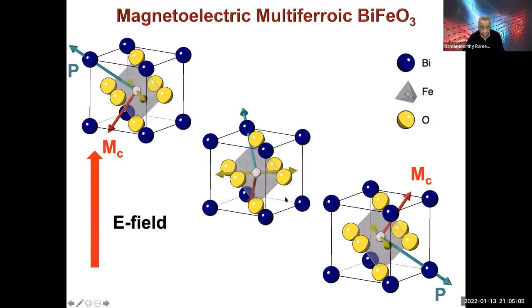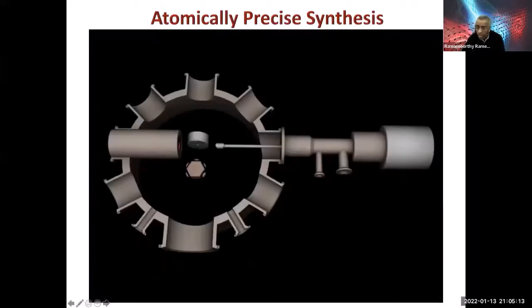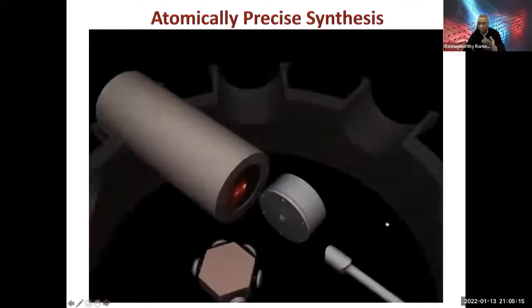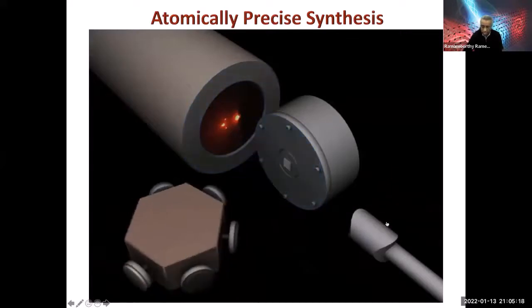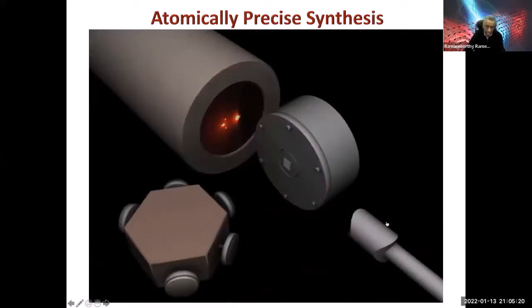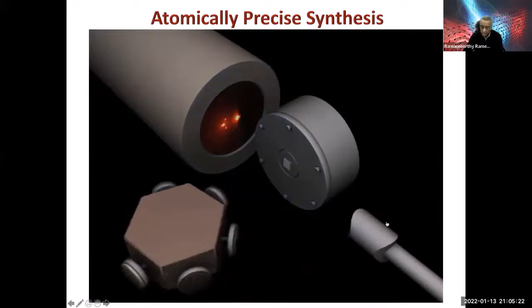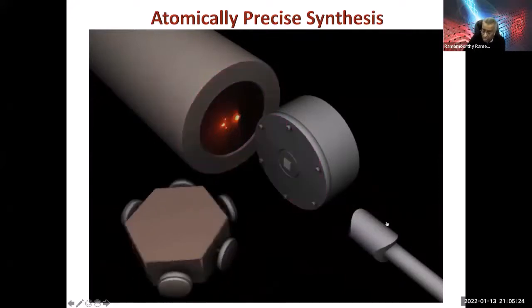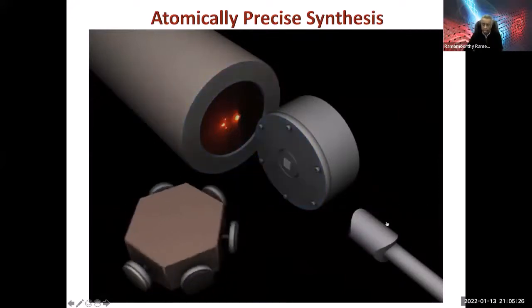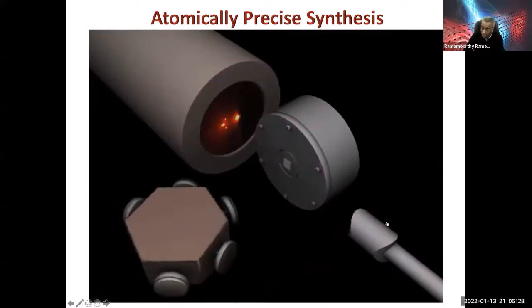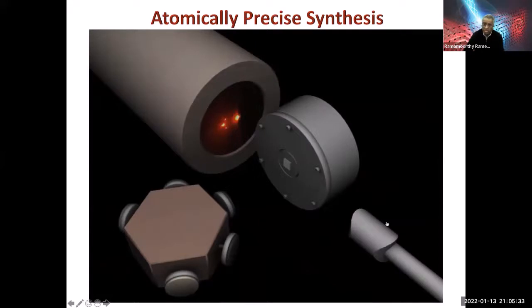Okay. But then with this work that we published back in 2014, it was now clear that indeed the canted moment was switching. And we use atomically precise synthesis, and many of you have this. Shubhankar has this system. Manuel Bibes at Thales has this as well. It's called laser MBE. We work very closely with Darrell Schlom at Cornell to do regular MBE. So we now have the power to synthesize these materials essentially at the atomic scale.